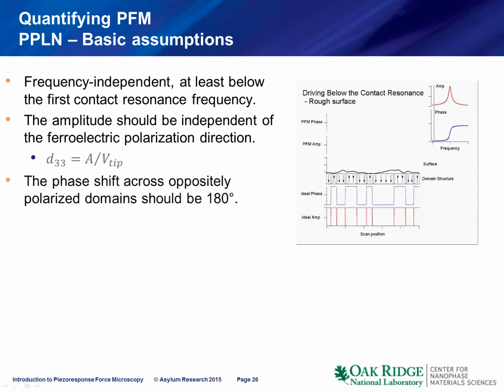That was really the model, if you recall, from the first webinar: if you have a sample like that, the phase should switch between 0 and 180 degrees as the tip flies over it, and the amplitude should be at a constant value and then go to 0 in between the domain boundaries. I can play that movie just so you remember that. Now, if you drive below resonance, of course, there's some noise and so on. So the PFM phase has some noise in it, and the amplitude has some noise in it. And, of course, in real samples, the roughness and so on can corrupt that measurement a little bit,